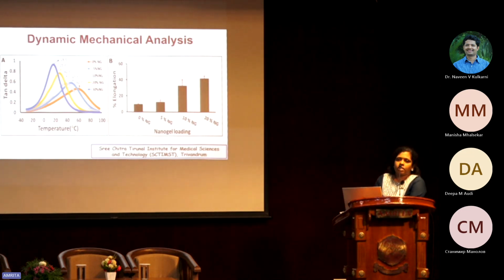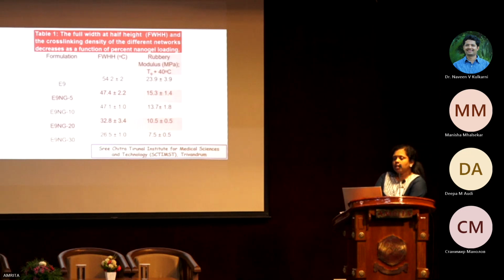We also checked the percentage elongation. Of course, if we are introducing additional cross-linking and the Tg is reducing because of this plasticizing effect, the percentage elongation is also increased, and it is also confirmed from this graph: as the nanogel loading percentage increases, the percentage elongation is also increasing. And the rubbery modulus we also checked at Tg plus 40 degrees Celsius, and it shows that the rubbery modulus is reducing with the nanogel concentration, but it's okay. For that particular application, the modulus is good enough because it is still in MPa.